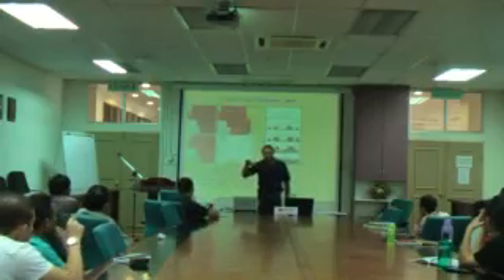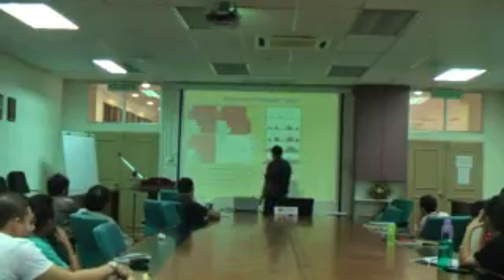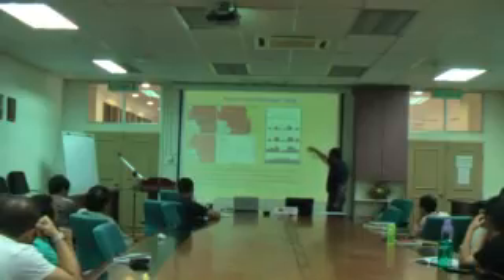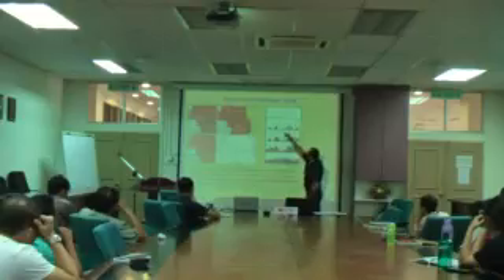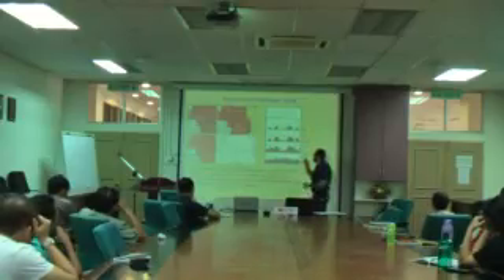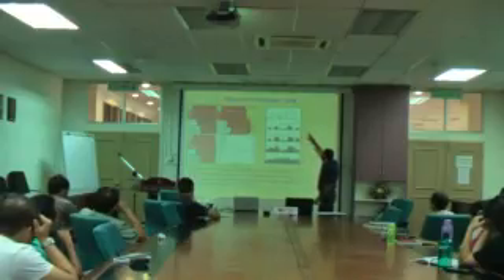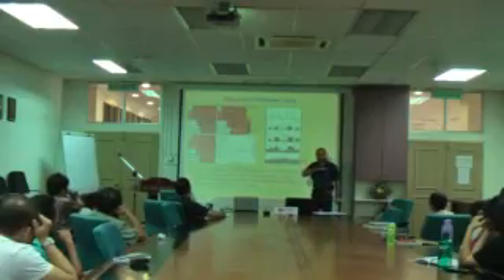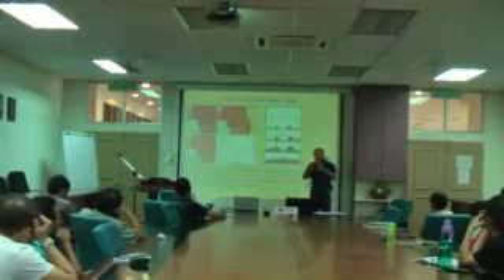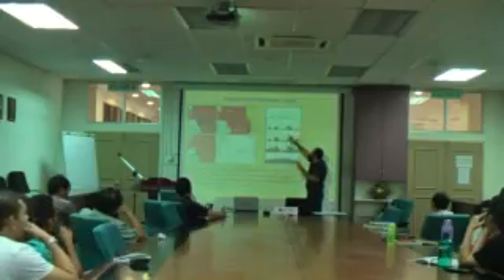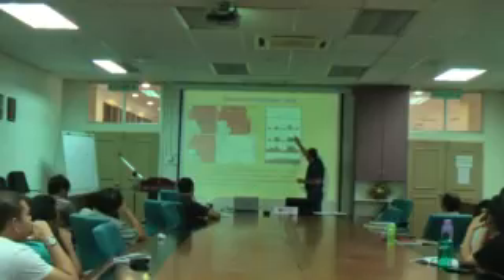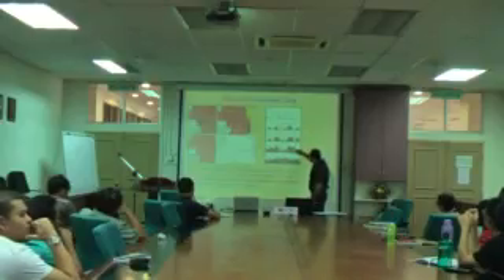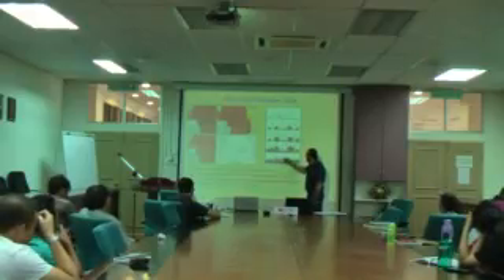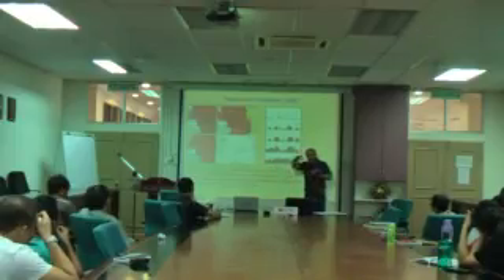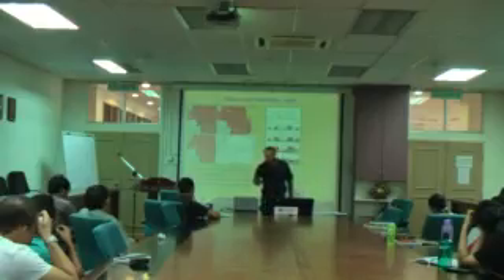And these are the last category of our sample. We vary the germanium top layer. This is a schematic diagram for growing, for increasing the top layer germanium. These are all germanium, these black dots. So first, because they have kinetic energy, they move in the surface, they find the nucleation site and grows, nucleating. Then by increasing, this is a coalescence and agglomeration of some of these kind of materials, they become larger. Then again, by further deposition of germanium become larger, then the other atoms, when they come to this one especially, they create a new nucleation site on top of this germanium and create this feature.